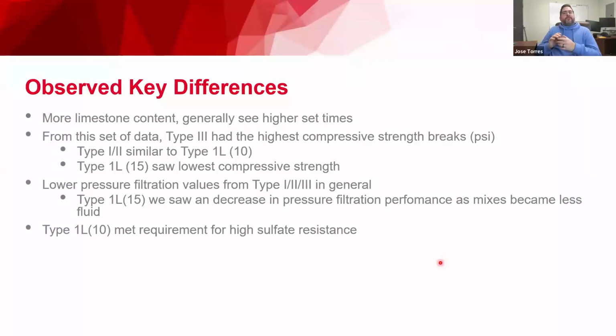We also saw that type 3 had the highest compressive strength breaks. If you go back to the table where we compared the mill certs, that was kind of expected from what the manufacturer's recommendations were saying. Type 1-2 was very similar to type 1L in terms of compressive strength, and type 1L at the 15% content saw the lowest compressive strength.